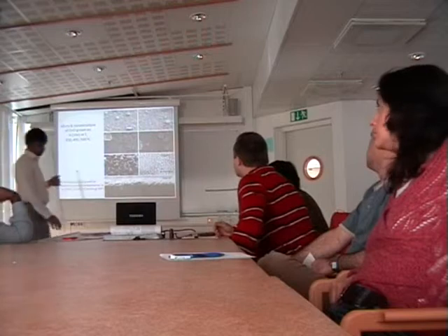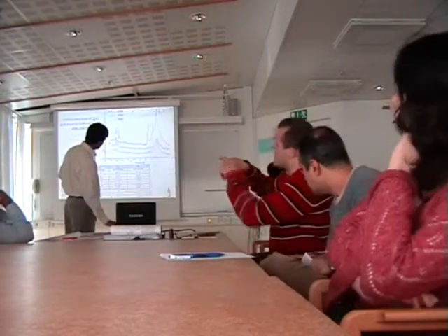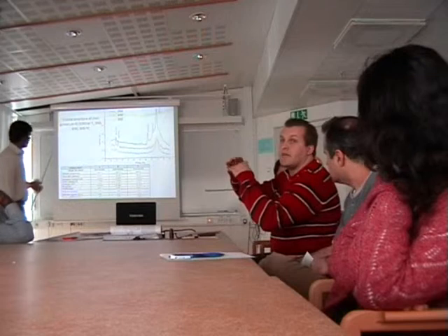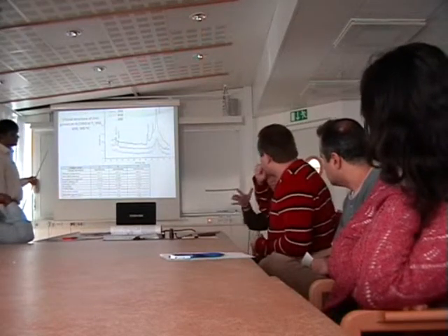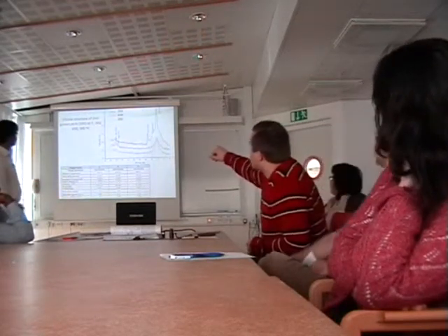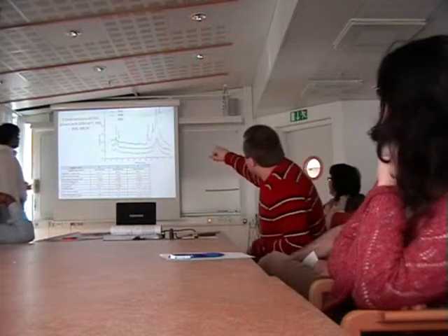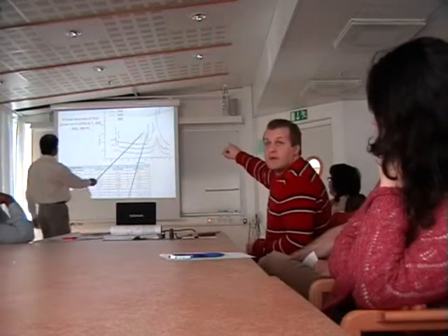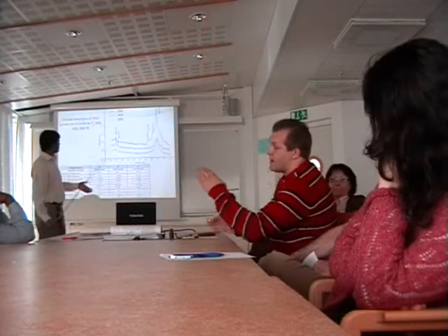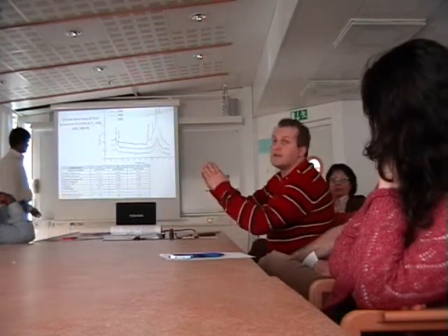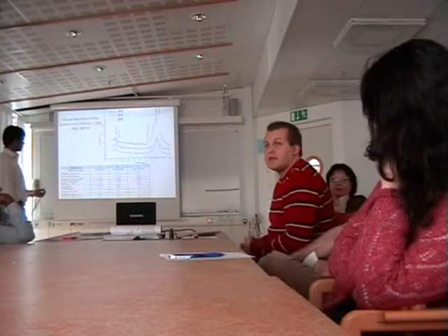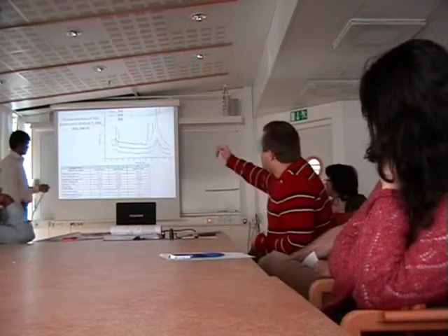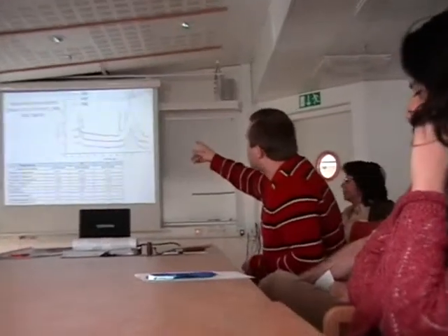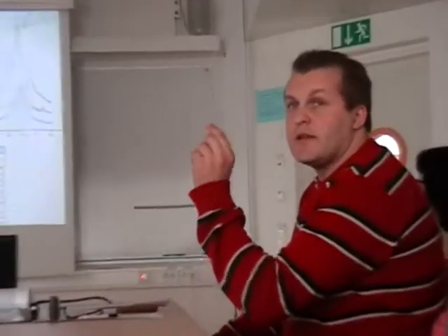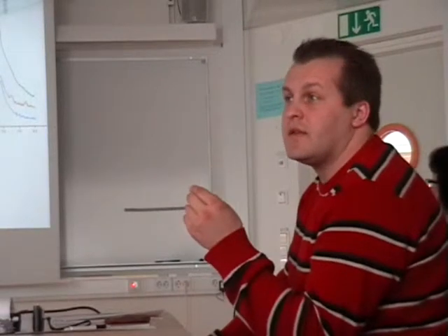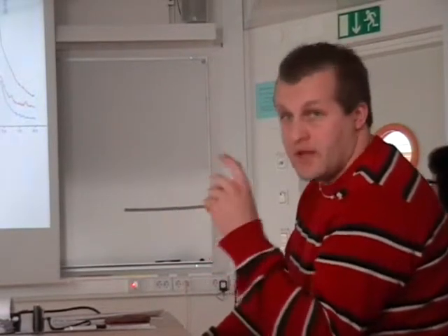Can I have a look at the XRD spectra? Because you see it's like a triangle structure before nanopillars formation. Slight faceting. So we strongly believe that these additional peaks, 103 and 112, are due to these tilted facets at the beginning of nanopillars. But if you look more attentively at the 002 peak, it's still really narrow, and we believe that this one is a contribution from the nanopillars themselves.